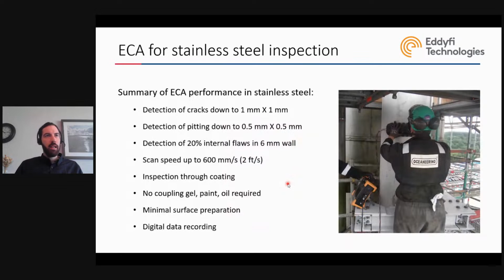So this is my last slide. If we summarize the performance of eddy current array in stainless steel, the cracks we were able to detect down to 1 millimeter by 1 millimeter. This will depend on the surface condition, but in the best cases, we'll be able to find this. Pitting corrosion down to 0.5 millimeter by 0.5 millimeter. Detection of 20% internal flaws in 6 millimeter walls, so up to 6 millimeters.